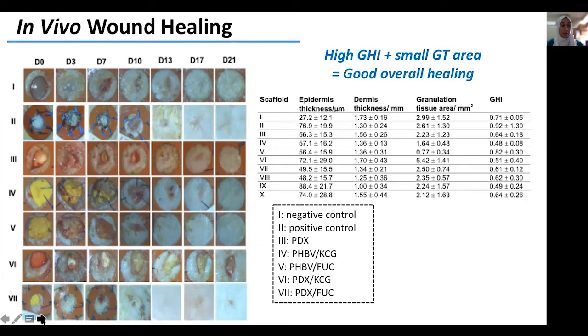Now, if we look closely at the first 2 scaffolds, we see that the wounds did close after 21 days, but we had the formation of a scar. In comparison, in the scaffold treated groups, we do not see the formation of scar at the end of the wound healing process. And if we look even more closely at scaffold 5, we see that there is no scar formation at all right from the start of day 13.